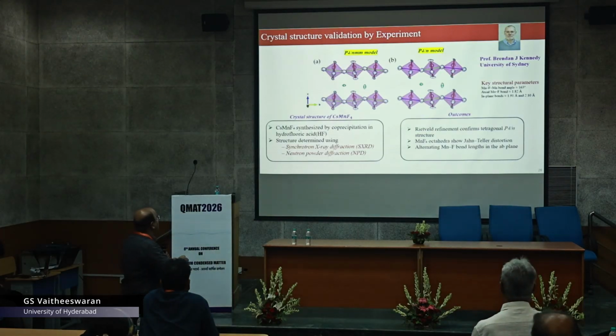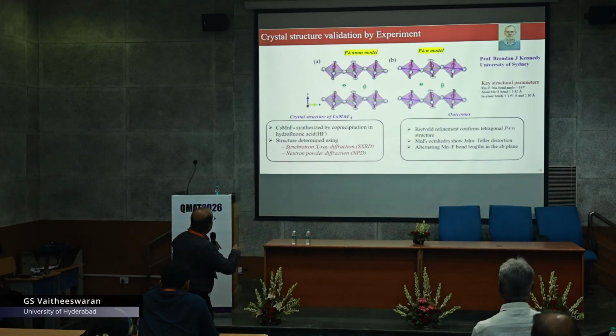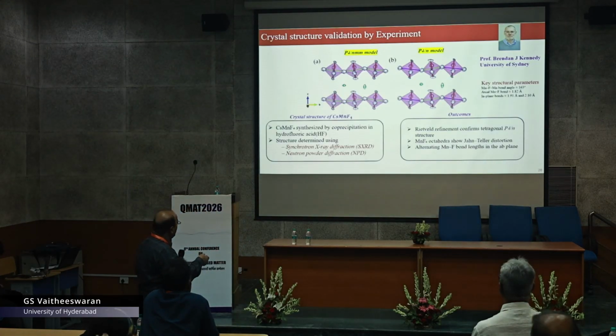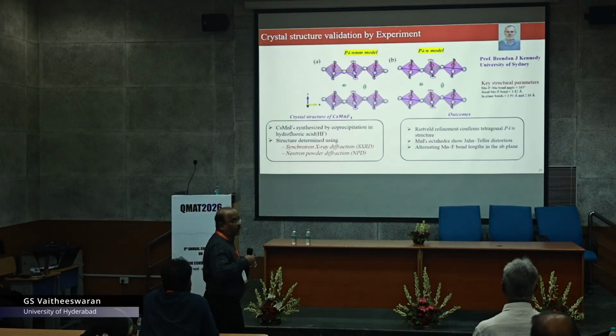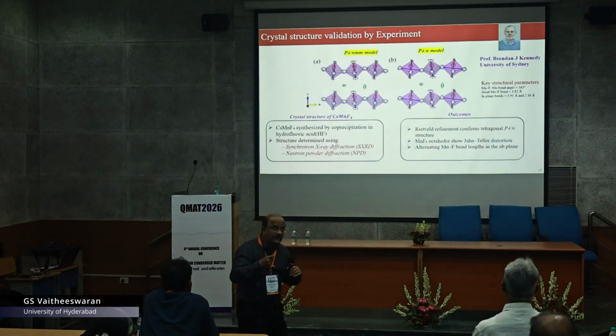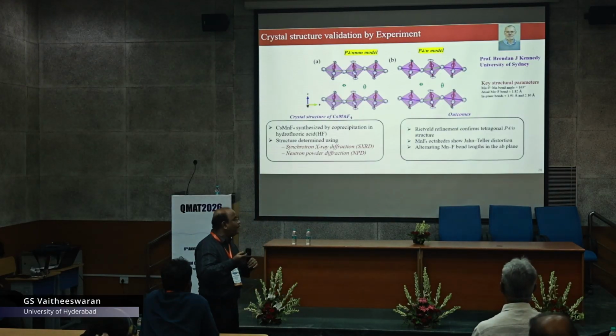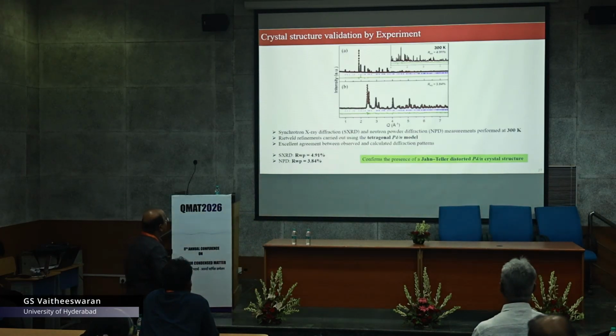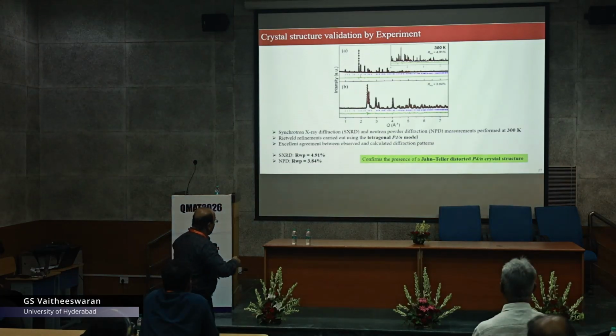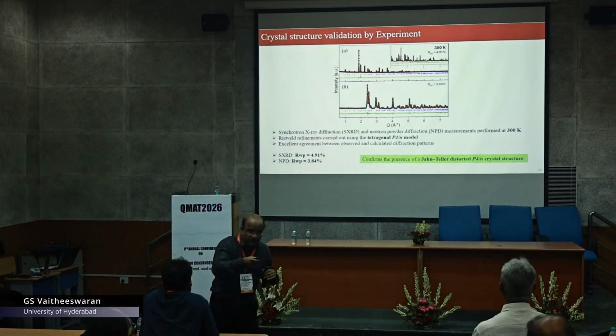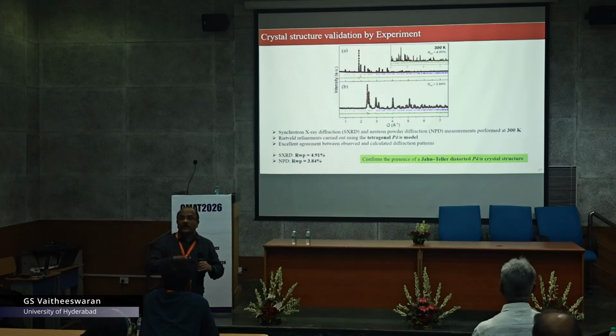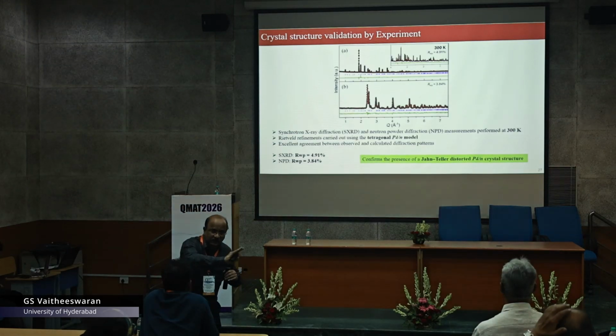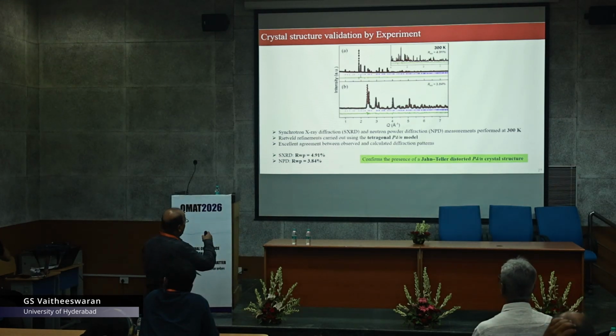fit these two models which were proposed, the P4/nmm as well as the P4/n model. He took synchrotron X-ray diffraction as well as temperature dependent neutron diffraction in Australia, and they could confirm that the tetragonal P4/n model which we proposed from the theoretical calculations is exactly matching with the experimental X-ray as well as the neutron diffraction.